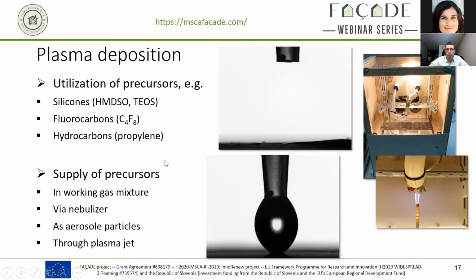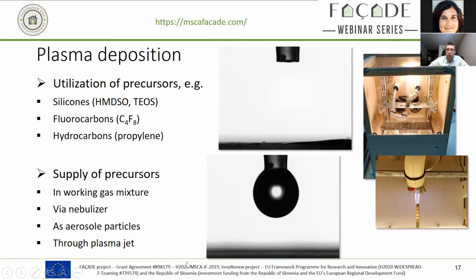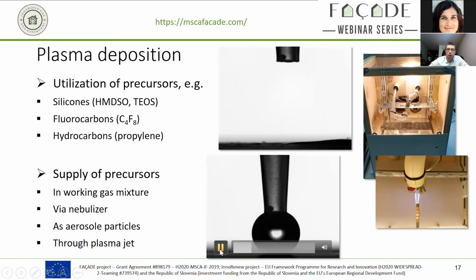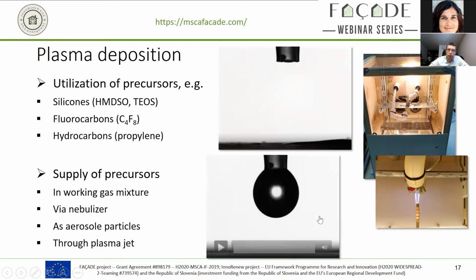On the top side, we see the contact angle measurement for a hydrophilic sample. When the drop is lowering, you will see directly upon impact, it's spreading across the surface and even spreading within a single frame, so that there's barely the possibility to even measure the actual contact angles. So this is one sample that definitely falls into the superhydrophilic category, whereas for different examples, we find cases where the droplet is contacting the surface, but it's repelled so much that it's rather sticking to the tip of the contact angle measurement device.